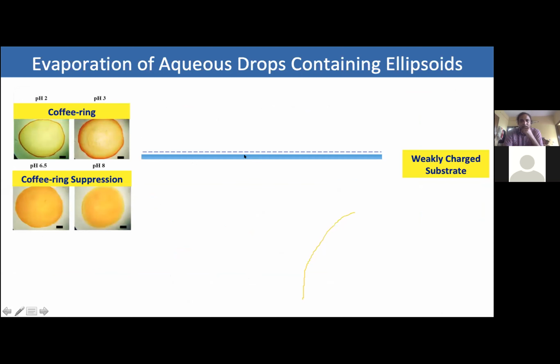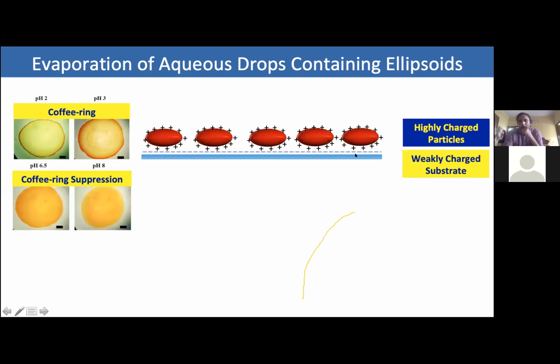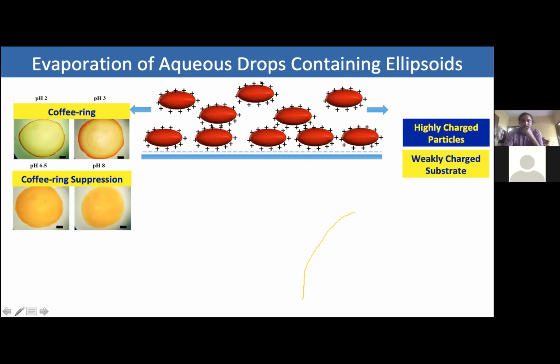So the way we understand these results is that if you look at the zeta potential plot at pH 2 and pH 3, the substrate is weakly charged. So that's what was evident. Now, of course, you have particles that are positively charged under these conditions, and even though the substrate is weakly charged, there could be electrostatic attraction that leads to initial deposition of particles on the substrate. However, once this is done, there are a lot of free particles available in the bulk, and these bulk particles are carried towards the edge, leaving a coffee ring deposit.